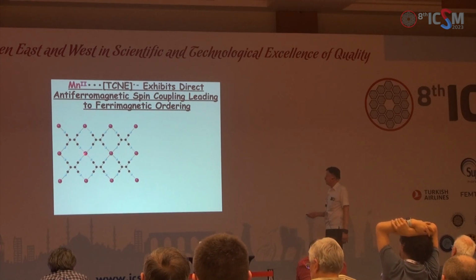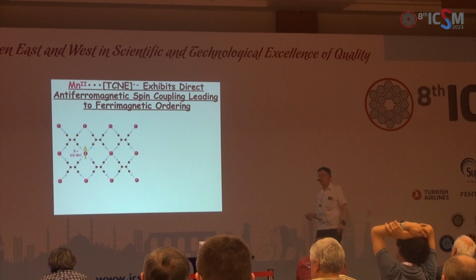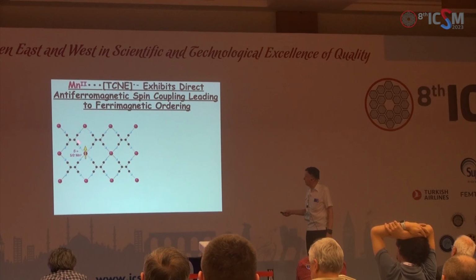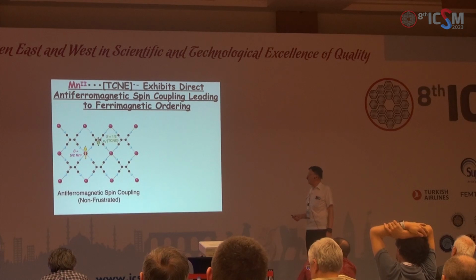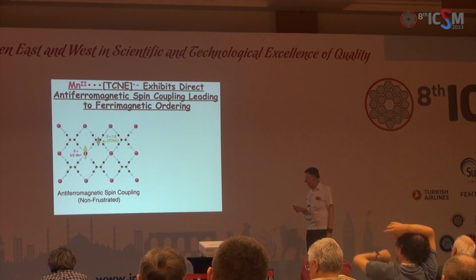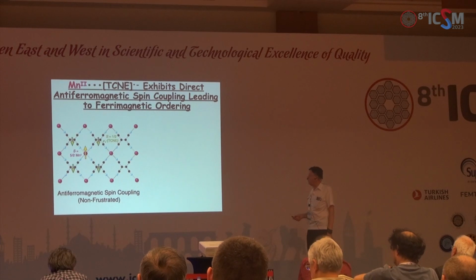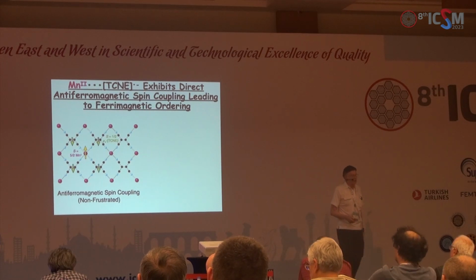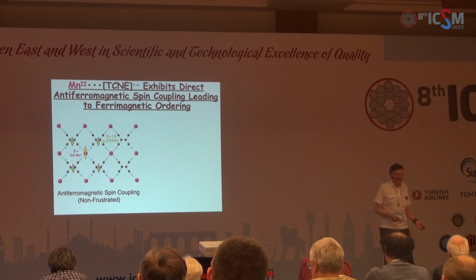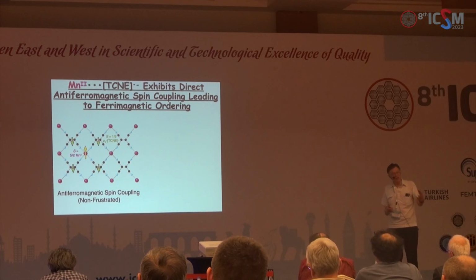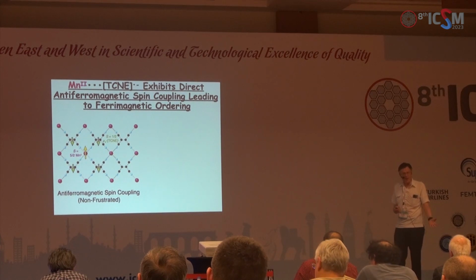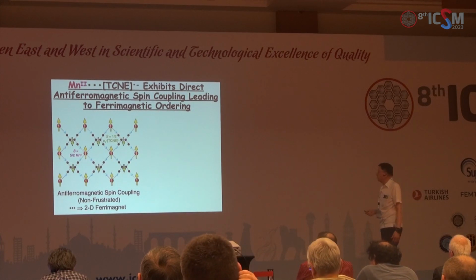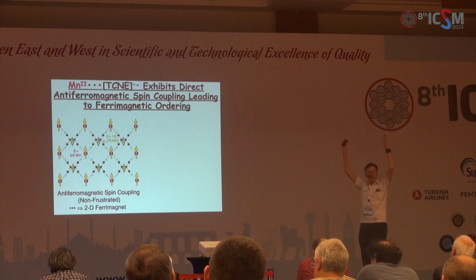Each manganese 2 site has got 5 spins, we'll call them up in yellow, and it's connected to a radical anion of TCNE with a spin in the p orbital, and that's antiferromagnetically coupled. Each manganese is surrounded by 4 TCNEs, so each of the 4 TCNEs are antiferromagnetically coupled, spin down. And each TCNE is surrounded by 4 manganese with spin up. So all the manganese spins, 5/2, are up, and all the TCNE spins, 1/2, are down.